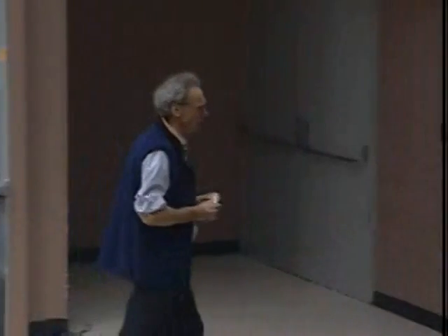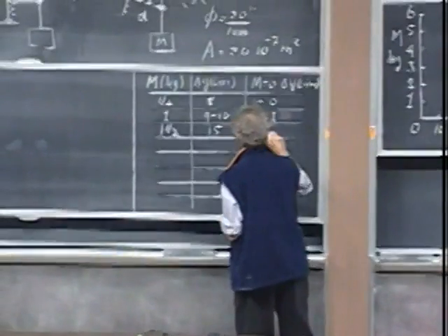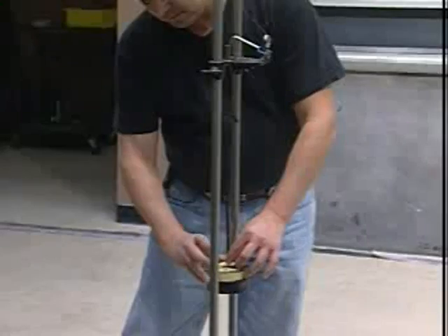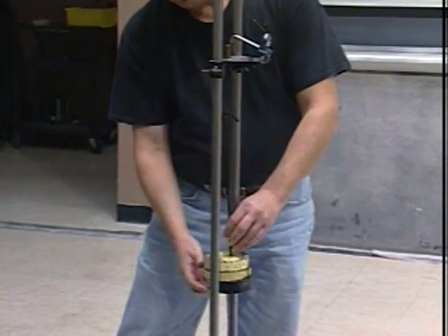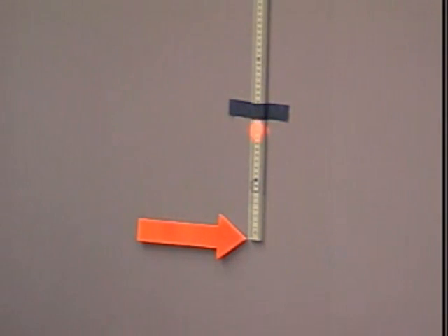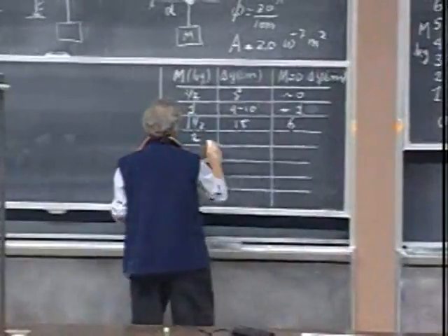Oh, but you see, it no longer wants to return to its original length. It's clearly longer now. Permanent deformation has already occurred. And so we are now at something like 6 centimeters. Can you make it 2 kilograms? If it's linear, you would expect near 20. And it's still amazingly linear. It's as close as I can see it to 20, but all these readings are no more accurate than half a centimeter or so. So can you remove the 2 kilograms?